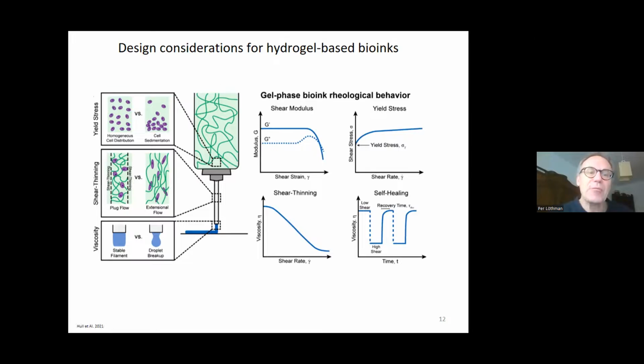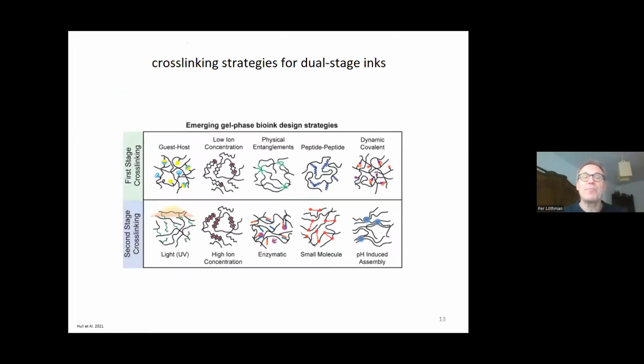is something that we have with the gel material, hydrogel material, but not with the sol material. This plug flow will prevent shear stresses from becoming dangerous, so to speak, since we have a lubricating layer. High viscosity will make a stable filament, as you can see here to the left below, and it will prevent droplet breakup.